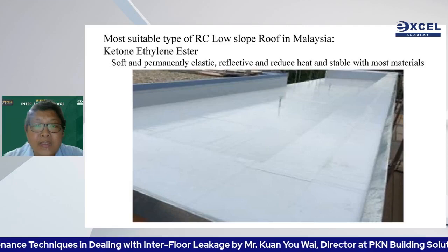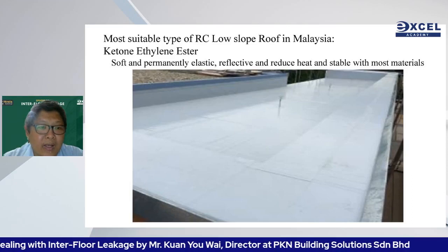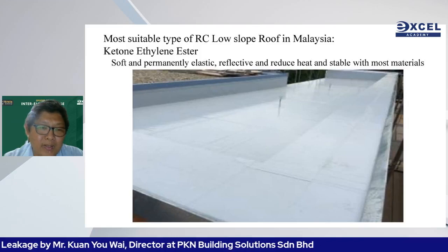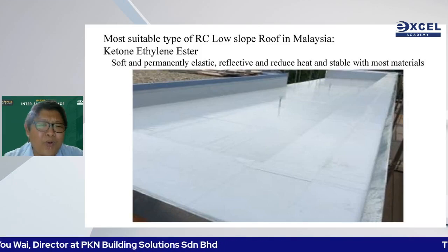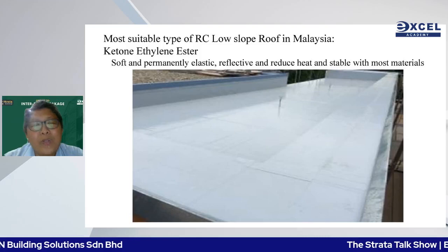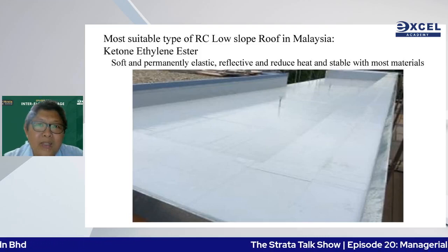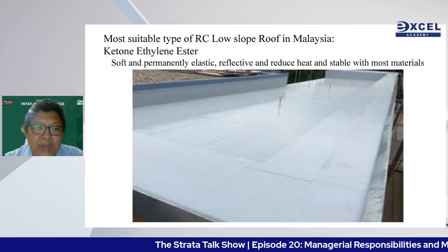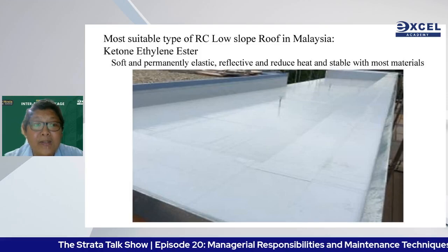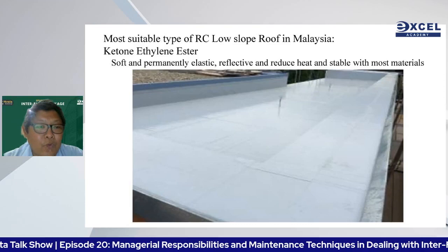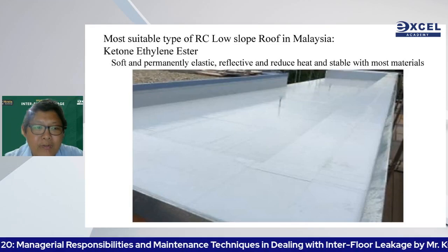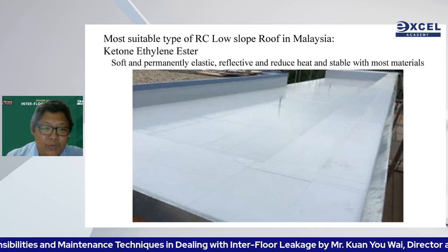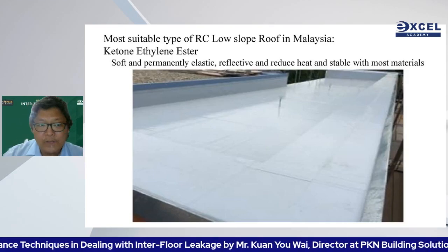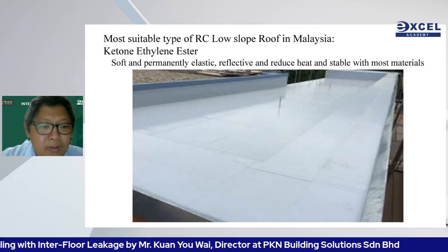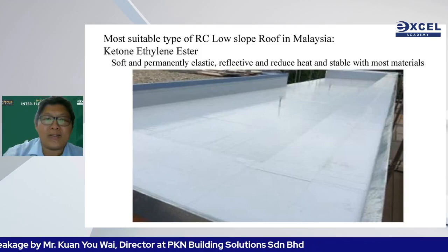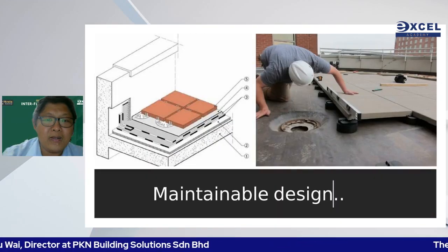In University Malaya, a group of students and I did an experiment on a small concrete roof on the University Malaya campus. We discovered at 1:30 p.m. the temperature was 82 degrees Celsius on average. 82 degrees Celsius, okay? At 4 a.m., it was 17 degrees Celsius. So the difference from daytime to nighttime is 65 degrees. If you multiply it with the coefficient of thermal expansion, it actually expands and contracts. Next slide, please. That makes elasticity so important.